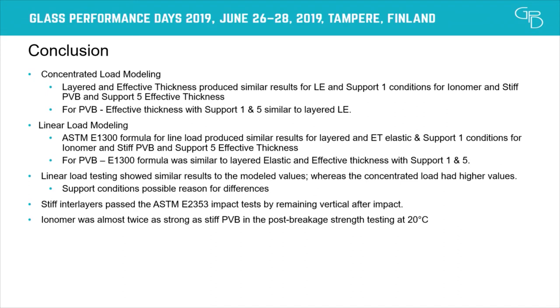The linear load testing showed similar results to the modeled values for the stiff interlayers, whereas the concentrated load, a little bit different. The stiff interlayers passed the 2353 impact tests after being broken, and the ionomer was about twice as strong as the stiff PVB on the post-breakage load. This was all done at 20 degrees C, so we probably need to redo that at different temperatures.